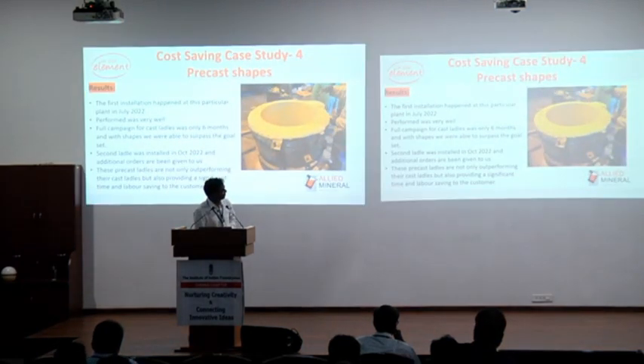So the first installation happened in July 2022. Performance was very good. Normally, cast ladles run for 6 months with regular maintenance. We had good success, and based upon that we installed the second ladle in October. These shapes are not only outperforming the cast ladles, but also save a huge cost by reducing downtime and savings in the labor part. And also, as I said in the beginning, these have been fabricated in a controlled fashion, so the slag sticking was much lesser compared to the as-cast ladles.